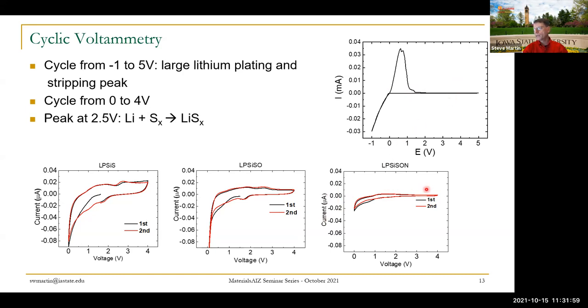Look down at the microamp and nanoamp, and that's where you really need to see whether there's any reactions going on. So these glasses look very stable, both at reducing potentials and at oxidizing potentials. So oxygen, nitrogen seem to suppress any of these side reactions, which we think are primarily excess sulfur. Maybe that's excess sulfur. Remember I talked about that phosphorus-phosphorus bond? Well, that sulfur's got to go somewhere. So maybe it's coming out into the glass.